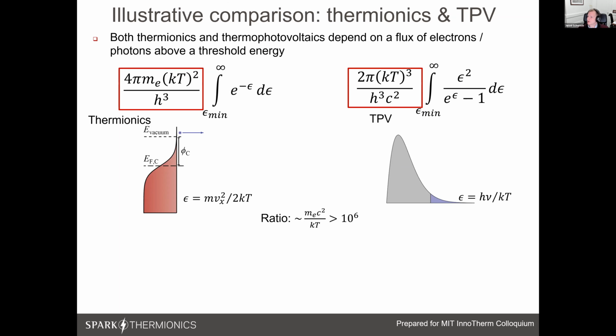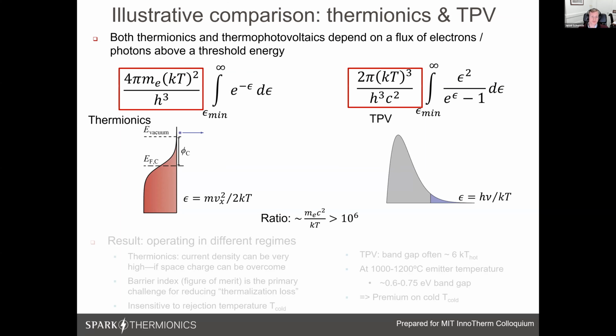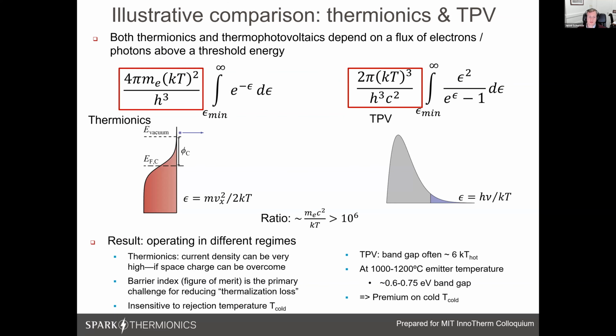And what that means is that despite the black box similarity of these technologies, we're actually operating in very, very different regimes. As you heard in the previous talk, a band gap in a thermophotovoltaic cell is often just a handful of kT, and of course the voltage out is just a few kT as well, kT hot, I should specify. And at the typical emitter temperatures that you'll see in literature, of course these can be much higher for energy storage applications, you're looking at a pretty small band gap, as Andrej reported, of 0.6 to 0.75 eV. And this really forces you to operate at a very cold collector temperature, which has implications for system level design and efficiency.